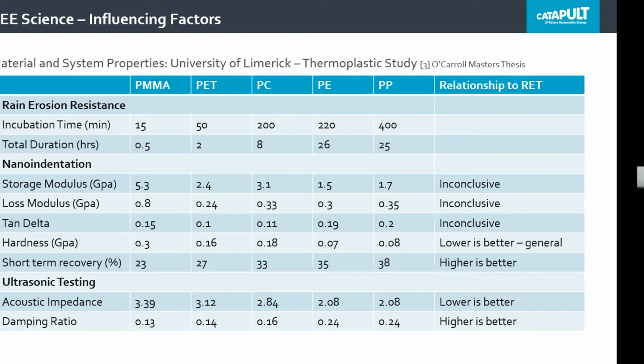For ultrasonic testing, they measured the acoustic impedance and the damping ratio, and found that for thermoplastic materials, it's better to have a lower acoustic impedance, which is saying that the sound waves are traveling through the material, and that the higher damping is damping these sound waves out.